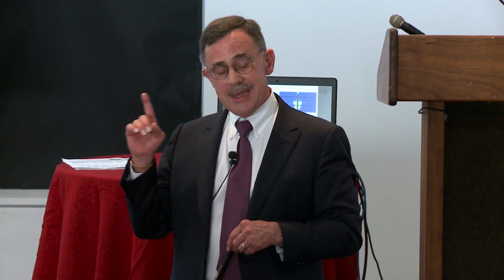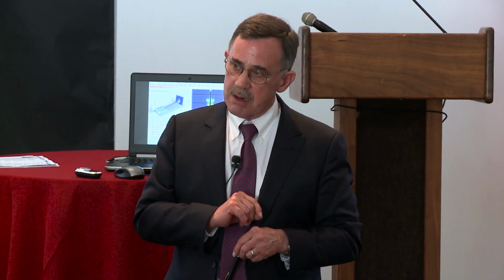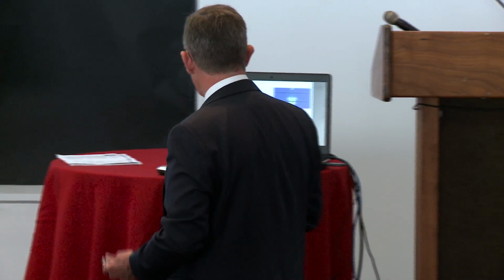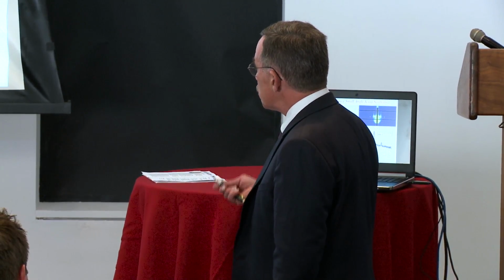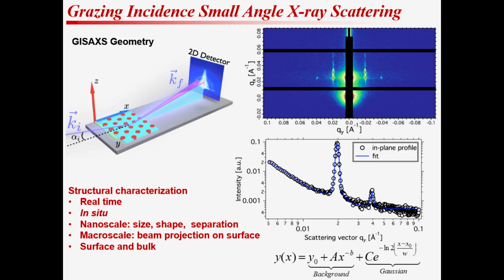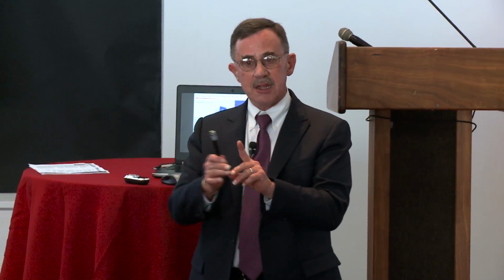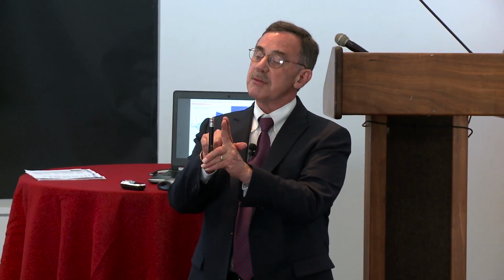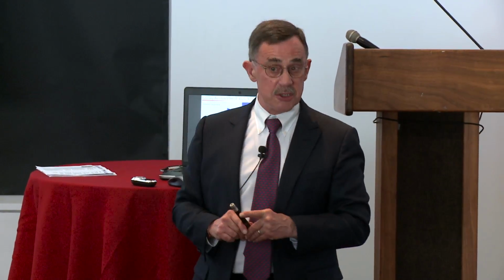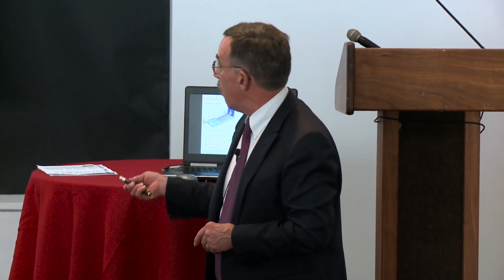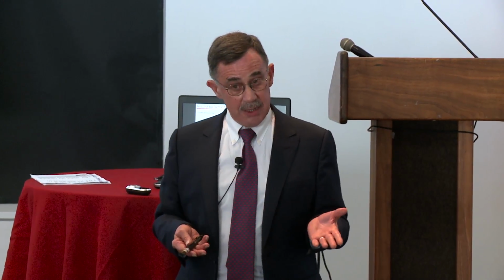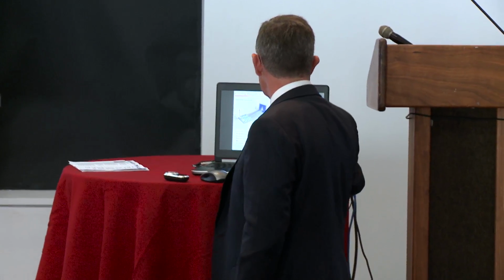It's not perfect. I can't tell you if I have 1 defect or 2 defects or 10 or exactly where the defects are, but I do get an average measure of the overall ordering in the material. From the spatial position of the reflections, think if I have cylinders standing normal to a surface, what that's telling me is I have an interference arising from the center to center distance between these domains. So I see a peak or multiple peaks depending upon the overall order in the material. So it's a very easy means by which I can tell you how big the structures are, what their separation distance is, and how well ordered these particular materials are.